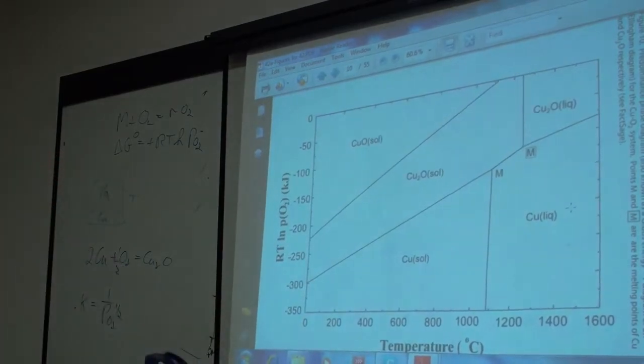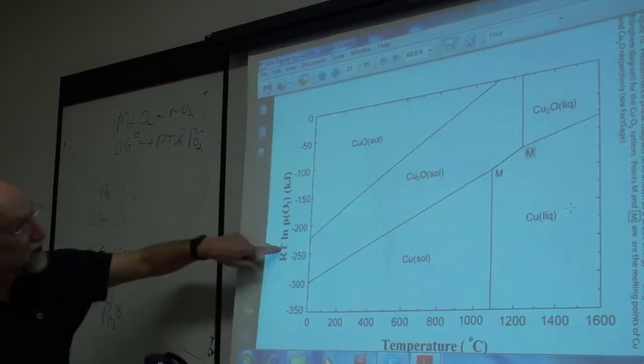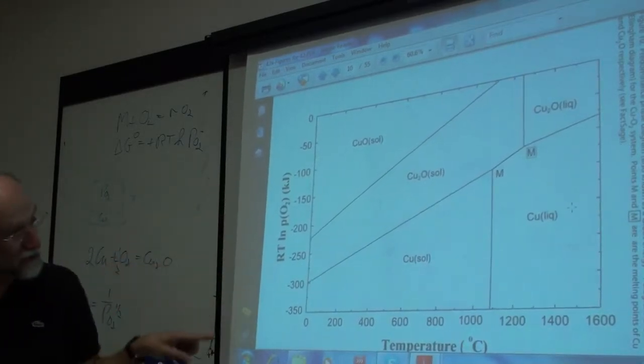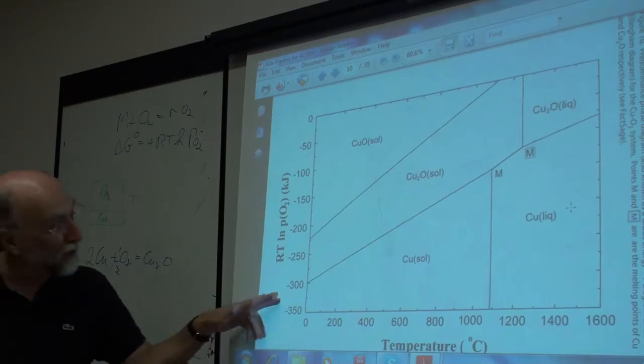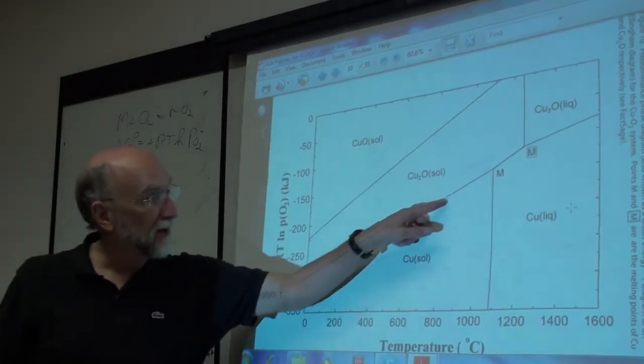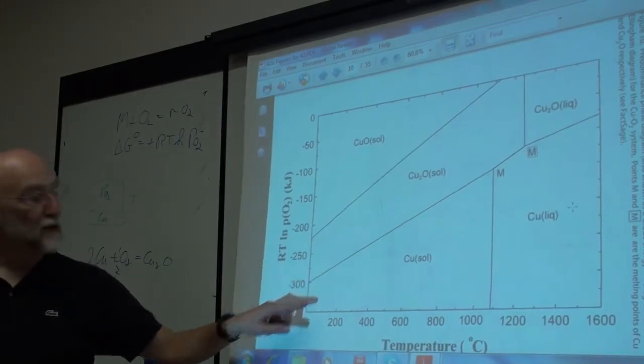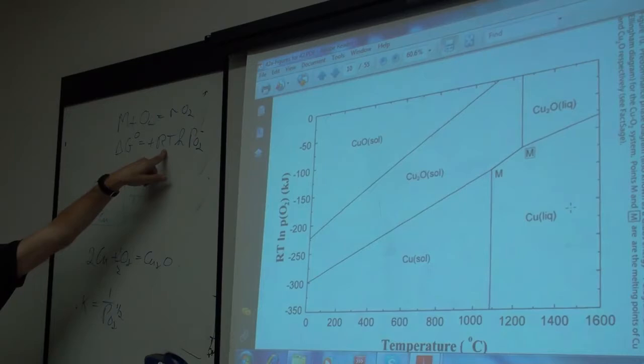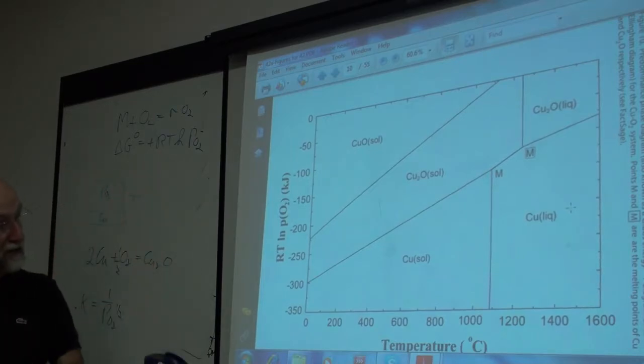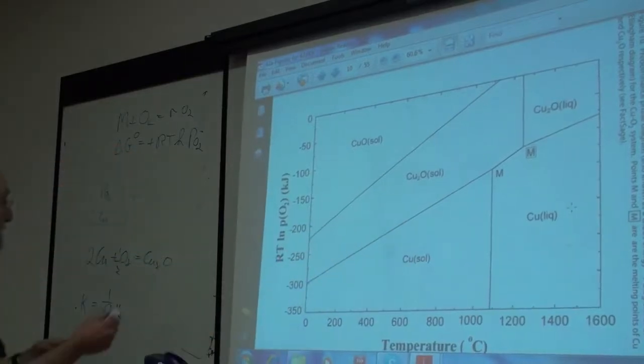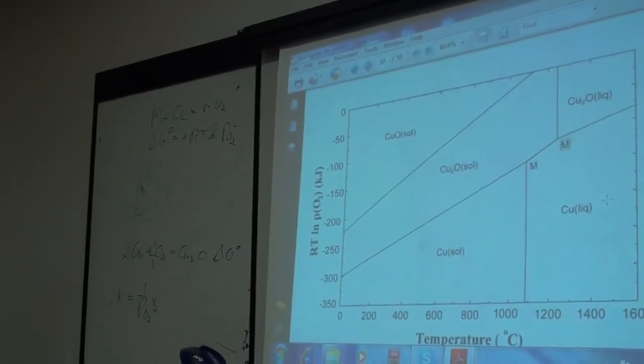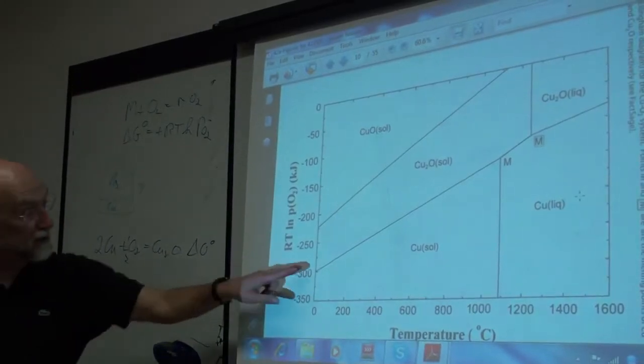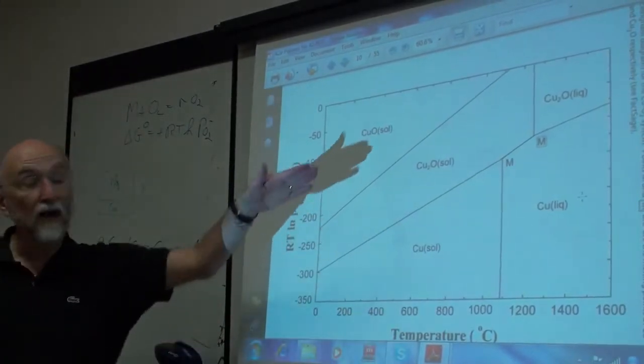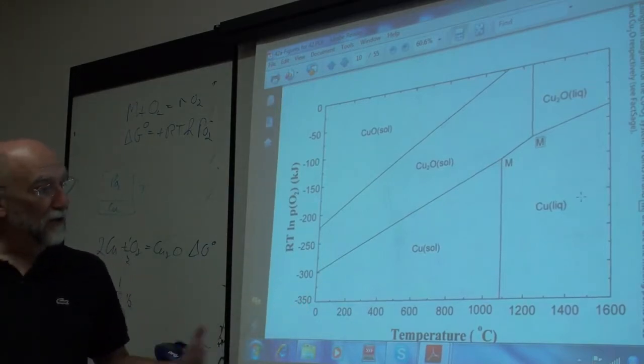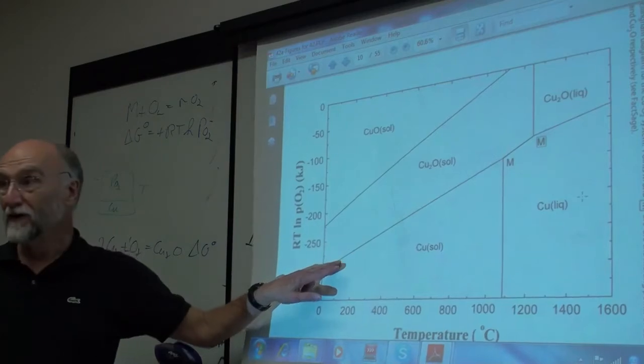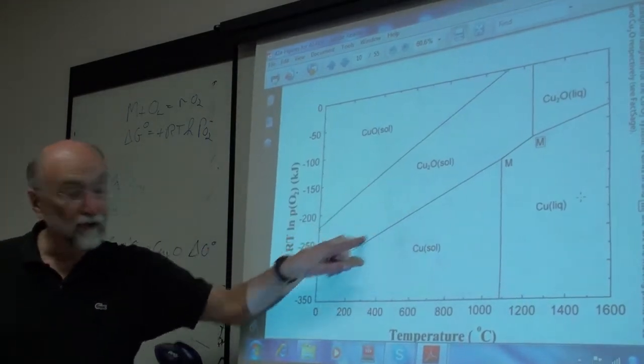This is the line where the two phases are in equilibrium. In an Ellingham diagram, what you do is you plot the Gibbs energy of formation, delta G0, versus temperature. So you don't look at this as a phase diagram, you look at this as simply a plot of the Gibbs energy change as a function of temperature. But the Gibbs energy change is RT log PO2. So an Ellingham diagram can be looked at as a curve of delta G standard for this reaction. This is the way an Ellingham diagram is presented: I'm plotting delta G0 as a function of temperature. This is just a line on a graph of delta G0, or the other way of looking at it is, this is a phase diagram and this is a phase boundary. Here you have a one-phase region, and you have a two-phase boundary.